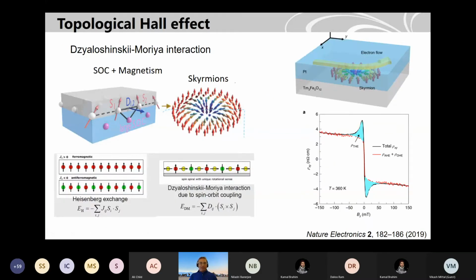Another thing, since it's a topological workshop, it will be interesting to show how topology behaves in magnetic systems. As you know, you have spin orbit coupling. Let's say you have a magnetic material, but some magnetic materials have low spin orbit coupling. If you bring your magnetic material in close proximity with a high spin orbit material, for example platinum, and here is a ferromagnet, for example cobalt, nickel, or iron, what can happen at the interface? At the interface, your spins will experience more spin orbit coupling.